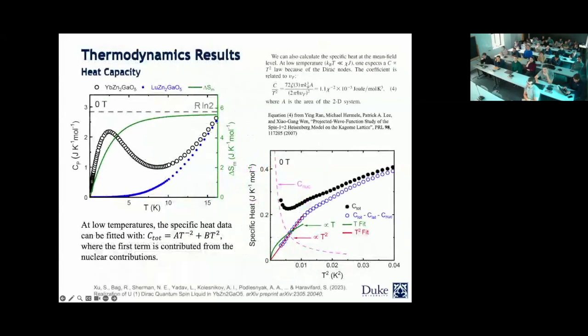Okay, so the next thing that we checked is basically to look at the heat capacity. And this actually turned out to be quite important. The first thing to check is, down to 50 millikelvin, is there going to be any ordering that we would be able to see in the specific heat? And of course, we didn't see anything. You're looking at the total specific heat as a function of temperature at zero field here, and you can see that there is a Schottky type of peak that is popping up.